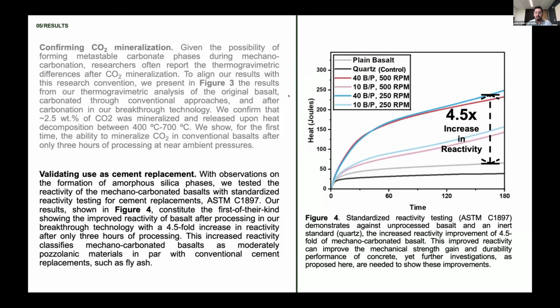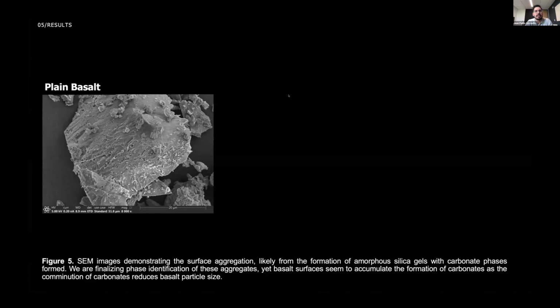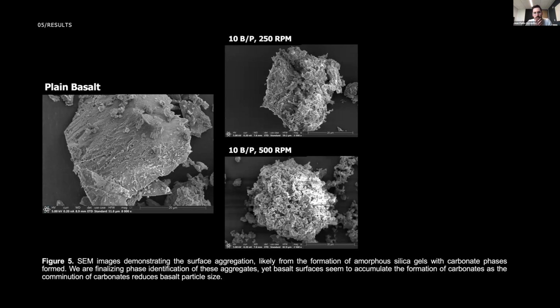But in order to do that with further engineering, we really need to start looking at the microstructure and understanding the mechanisms. This is where we have been spending a lot of time in the lab, looking at how these mechanisms differ when we change a lot of these variables. Here is an SEM picture of just basalt. This is just a plain basalt particle. When we do mechanical carbonation on basalt at a 10 ball to powder ratio and increase the milling energy, you can see that the surfaces are quite disrupted. And interestingly, we have aggregation of smaller particles or clusters around the surface of this basalt.